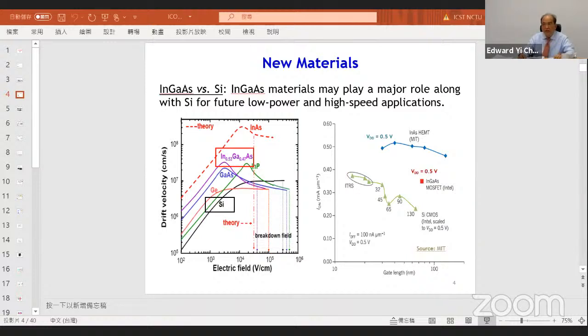And the challenge of these devices is that the device scale is very small. One of the possible problems is the surface. If the surface is rough due to the etching, and you have a lot of sidewall damage, then the mobility of the device will be degraded, and you will have rough sidewalls and surfaces.